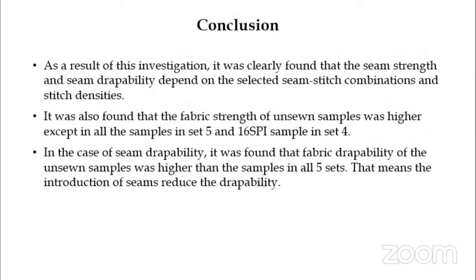The last part is conclusion. As a result of this investigation, it was clearly found that the seam strength and seam drapeability depend on the selected seam stitch combination and stitch densities. It was also found that the fabric strength of unsewn sample was higher except in all the set samples in set 5 and 16 SPI samples in set 4. In the case of seam drapeability, it was found that fabric drapeability of the unsewn samples was higher than the samples in all 5 sets. That means the introduction of seam reduced the drapeability.